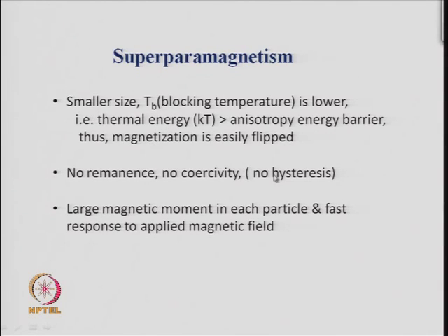Apart from that, there will be no hysteresis in super paramagnets, there will be no remanent magnetization, and no coercive field. The H c will be 0, the M r, which is the remanent magnetization, will be 0, and a large magnetic moment in each particle will be there. The magnetic moment of each particle will be like the collection of the magnetic moments of the dipoles which are present in the particle. So, it will have a larger magnetic moment.